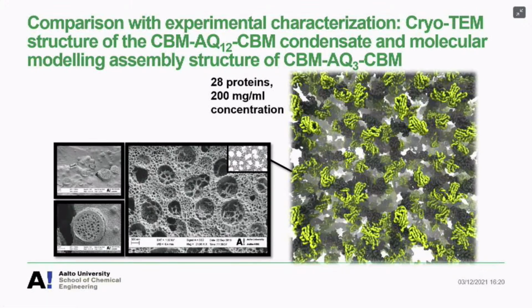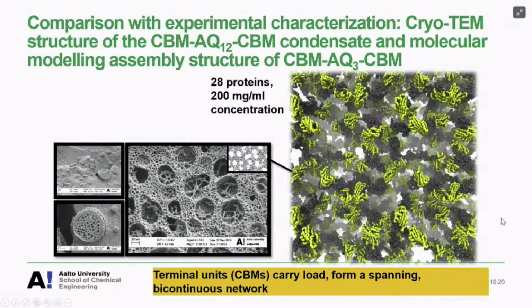We did even larger systems, so 28 proteins, 200 milligram per milliliter concentration, and analyzed this one for similarity with the experimental structure. What is coming out there is that we get a pore size that's shifted to a smaller scale than the experimental size. But remembering that the experimental protein is 12 units and the simulated one has only a 3-unit middle part, it's matching pretty consistently the structure that one could envision from the cryo-TEM. So the conclusion here is that the terminal unit CBMs are bearing the load. They form a spanning bicontinuous network for this